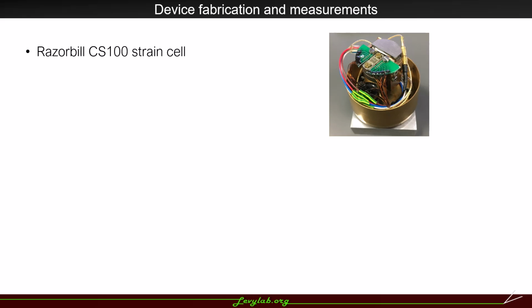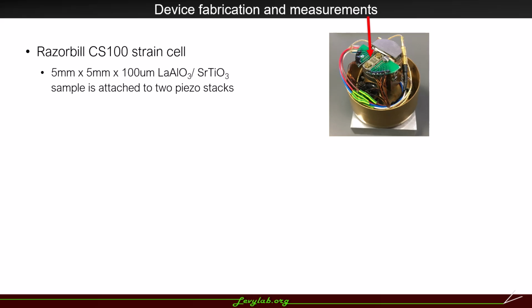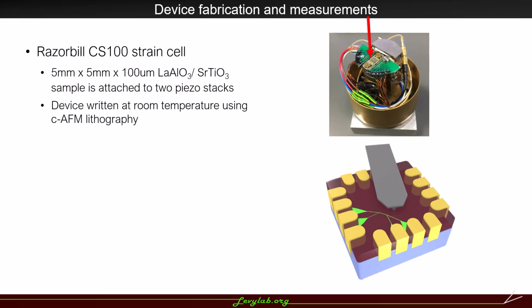For strain engineering, our experiment uses a strain cell by Razorbill company. From the picture on top, you can see our 5 mm by 5 mm sample attached on 2 piezo stacks in the strain cell. We create a 4-terminal nanowire device at room temperature and do strain-dependent transport measurement at 50 millikelvin, which is below the superconducting phase transition temperature for the system without any strain.